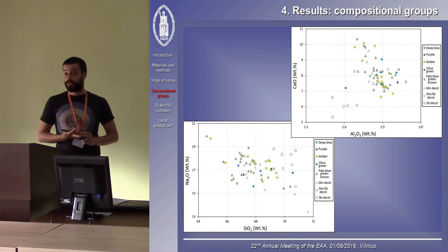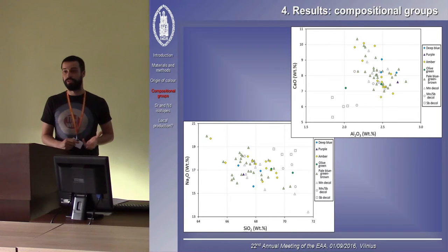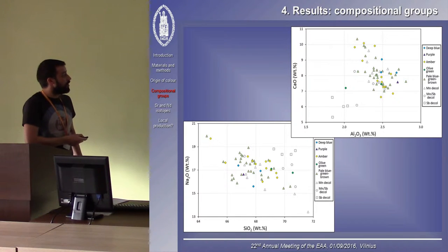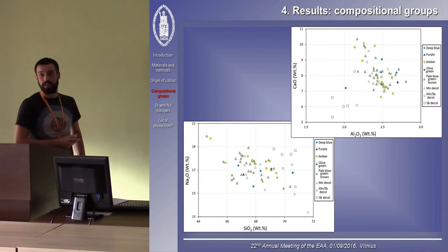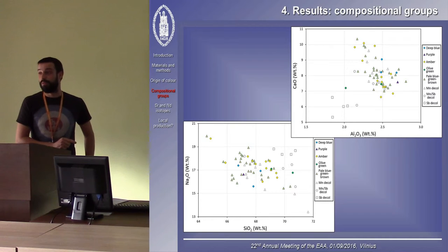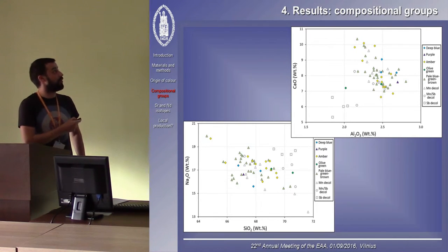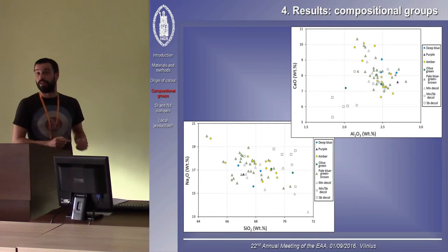The major elements in glass are silica, soda, calcium, and aluminum. When we want to distinguish different composition groups, these would be the first elements to look at. So here we have a silica vs. soda plot, and an aluminum vs. calcium plot. All the different colors of the glasses are plotted separately, and also our three colorless glass groups are depicted with different symbols. We can see that the antimony decolored glasses group very nicely together, both in the silica vs. soda plot and also in the aluminum vs. calcium plot. This suggests that they were made with a different sand source containing less amounts of calcium, so less shell or limestone, and also less aluminum, so less feldspars in the sand. But also a different recipe, because the silica vs. soda ratio indicates that these glasses were produced with a higher natron vs. sand ratio.